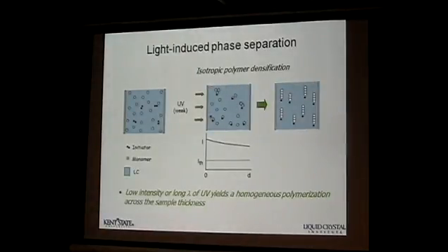And then sometimes if you can control this phase separation to be much slower, you can form them in the area where you want them to go. Okay. So instead of all localized, the threshold of this light intensity to form this phase separation is within the cell gap. This is the cell gap, the D. And then the light intensity across the cells is all above the minimum threshold. So it induces everything.